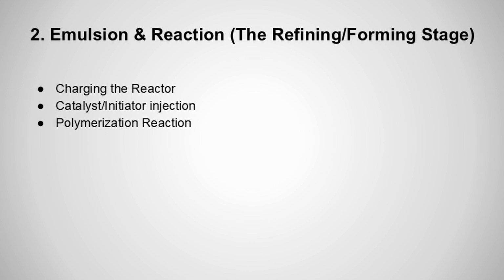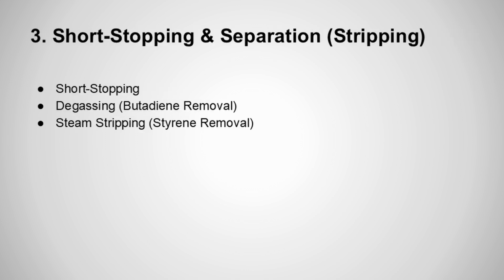Because the chemical reaction generates intense heat, a cooling jacket wraps around the reactor to strictly regulate the temperature, keeping it cold at around 5 degrees Celsius or hot at 50 degrees Celsius, depending on the grade of the rubber being made. To prevent the polymer chain from becoming brittle, the reaction is intentionally halted before all the ingredients are used up. Once the mixture hits a target conversion rate of 60 to 80%, a short-stop chemical is injected to kill the reaction. The remaining unreacted materials are then separated and recycled.